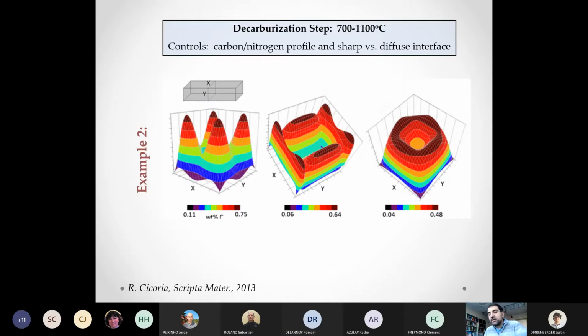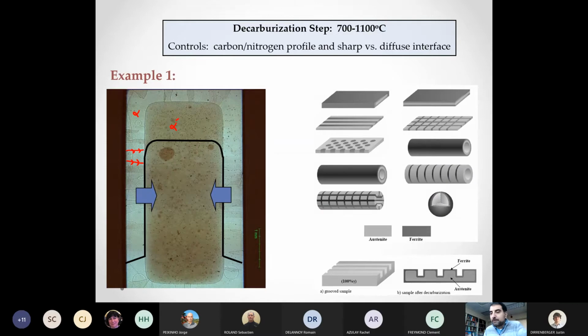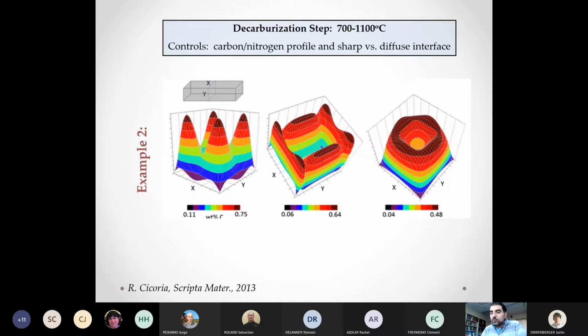So instead, we focused on examples where we don't have a sharp interface. And one of the things that we looked at is trying to see whether or not we can create more complicated shapes by applying masking steps, just like they would do, for example, in lithography, and create original distributions of the phases. And one of my postdocs, Dr. Cicoria, actually created an optimizer where you could tilt whatever profile you want and based on the parameters that our furnace can achieve, it will propose a schedule to get as close as possible to this profile.